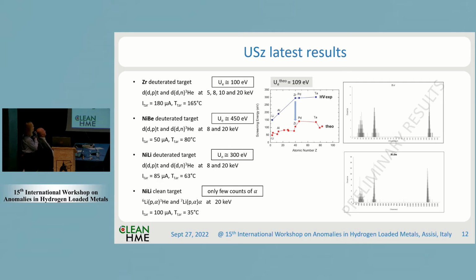We also used a nickel-beryllium deuterated target, and we got a good result, 450 electron volts. Unfortunately, the Mathe's group also studied that, and they did not have good information for us. They didn't reach those high values. Nickel-lithium deuterated target, again, around 300 electron volts, and a nickel-lithium clean target with the lithium P-alpha reaction. Unfortunately, these had too low statistics to say anything about the results, so I'm not even sure if we will take a look at that again.